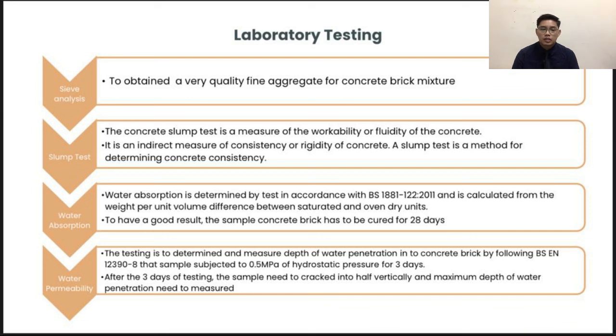And the last one is water permeability. The testing determines and measures the depth of water penetration in the concrete brick by following BS EN 12390-8, where the sample is subjected to 0.5 megapascal of hydrostatic pressure for 3 days. After the 3 days of testing, the sample needs to be cracked in half vertically and the maximum depth of water penetration needs to be measured.